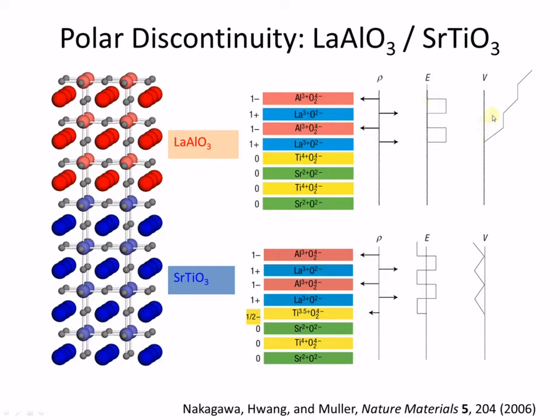And then you can integrate that electric field to see a potential that is linearly diverging with the thickness of the lanthanum aluminate. So this potential can get very large, and it in fact can lead to an electronic reconstruction. And when that takes place, the polarization of the lanthanum aluminate is screened in part by electrons that are bound to this interface, and that's represented here. So that polarization discontinuity can lead to the formation of a quasi-two-dimensional electron gas. And this was reported first in 2006 by Harold Hwang's group. Sorry, it was first reported in 2004. This diagram is taken from the 2006 paper.